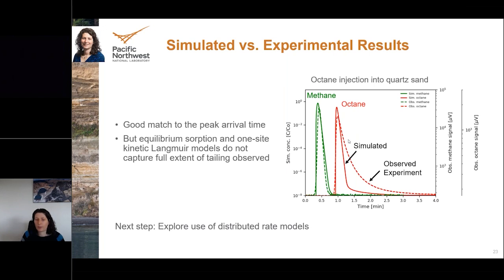And you can note how, especially with the octane, there's peak tailing in the observed experiment with IGC, but we haven't quite captured that tailing in the modeling experiment. We were able to match the peak arrival time well, so the max peak height and when that retention time occurs has matched well. But the models that we've done so far, the equilibrium sorption and the one-site kinetic Langmuir models, do not capture the full extent of the tailing observed experimentally.